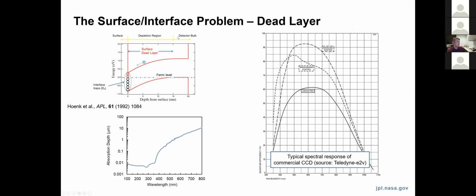And this has everything to do with the plots I'm showing on the left here, which highlight the absorption depth of photons in silicon as a function of wavelength. So at long wavelengths, these absorption depths can be in the micron range. As we go into the UV, they fall all the way into the nanometer range. And that's a problem because of the issue associated with the silicon interface. So silicon is a great material, and you can easily get a silicon wafer, for example, that has impurity levels in the parts per trillion, which is pretty amazing, with crystalline defect densities that have similar macroscopic scales.